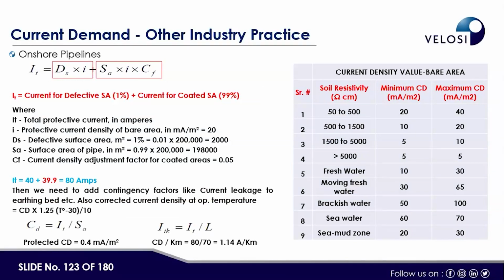The same is applied with the sacrificial and the impressed current. So here we are calculating, for this 100-kilometer pipeline, what is the current required according to the resistivity calculations. So this comes to 80 amperes, 40 plus 39 point something, using these ISO formulas. So with the 80 ampere current requirement, we can work out how much length we can protect. So 1.14 ampere is required per kilometer to protect these pipelines. Next.